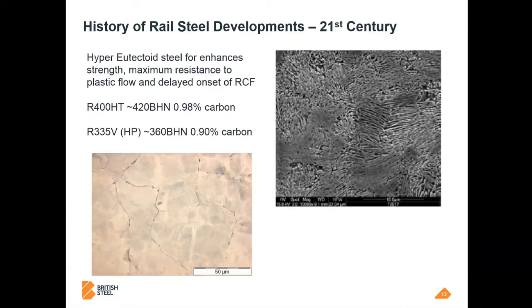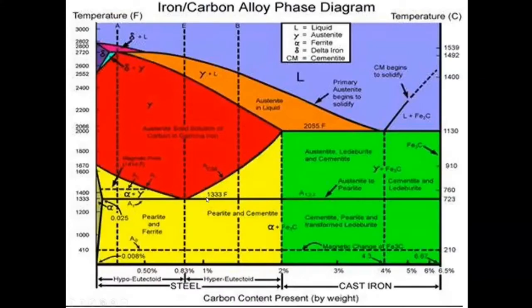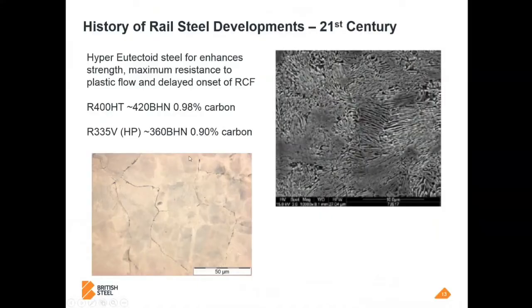Now, what the silicon does is it actually lifts this A1 line and it squashes this triangle, if you like. So if you trace up here, we're only at a very small temperature range anyway, but by lifting this A1, we squash it further and we actually suppress the grain boundary cementite formation almost entirely by alloying. And where does that carbon end up? Well, you end up with a higher volume fraction of cementite within your pearlite, which is desirable for the performance without a particular drop in its crack propagation rate.